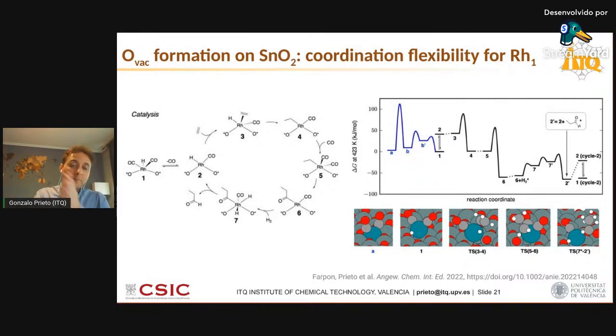Then should this mechanism depart to perform the competitive and undesired olefin hydrogenation, so ethylene hydrogenation to ethane, that departure could happen in between steps 4 and 5, where instead of coordinating CO, the mechanism would need hydrogen to be coordinated and inserted into the rhodium ethyl group to perform full hydrogenation into ethane. That's the undesired reaction. And we could compute that for this center, and again, thanks to the freedom that rhodium has, with this weak binding of rhodium to the oxide support, this hydrogen insertion is subject to energy barriers at least 50 to 60 kilojoules per mole higher than the CO insertion itself. Again, this is in line with the very high selectivity that we observe experimentally for this type of catalyst to hydroformylation, very effectively inhibiting the thermodynamically more favored hydrogenation of the olefin to ethane.